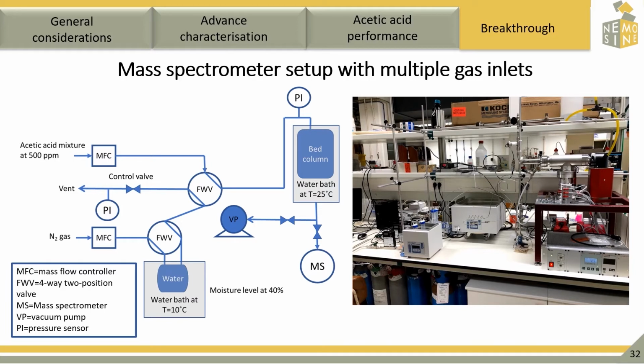This concentration was chosen since it was a compromise between the region of interest and the detection level and time of experiment. If we used a ppb concentration, it would mean waiting for hours or even days to saturate our column where the material is present. This packed column is also kept at controlled temperature with the help of the water bath.